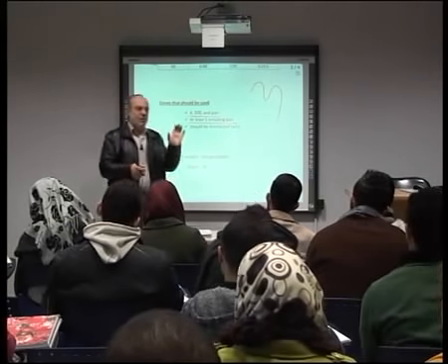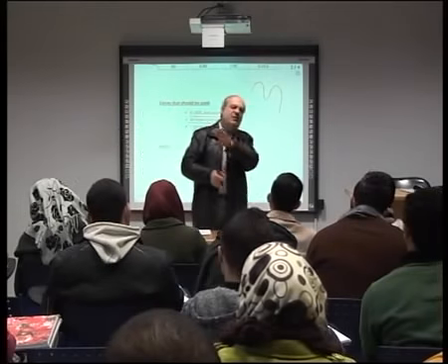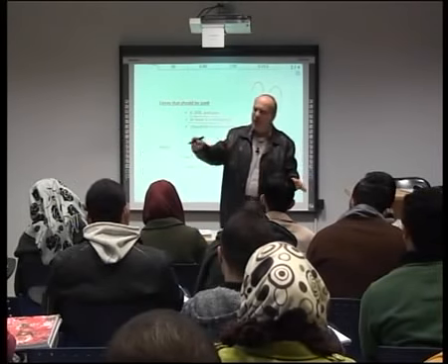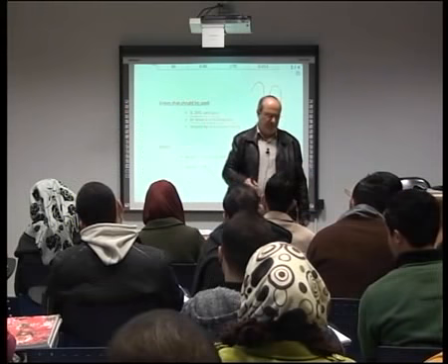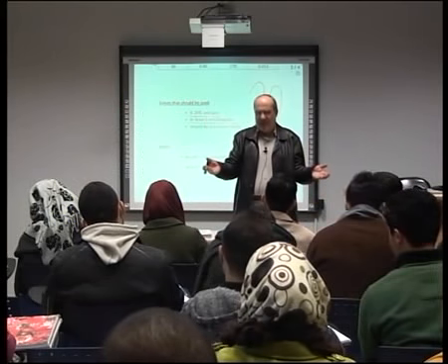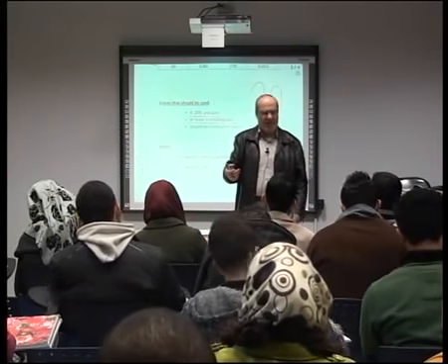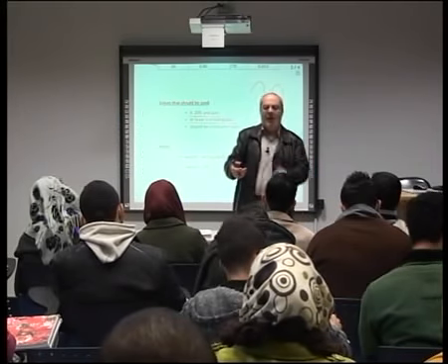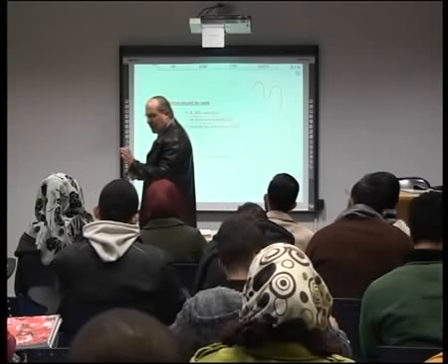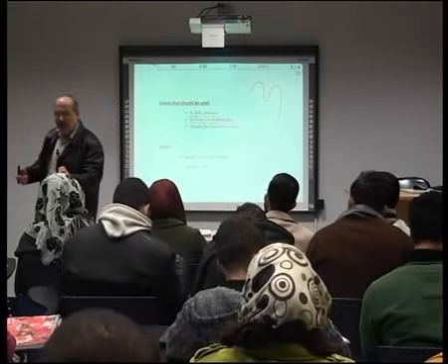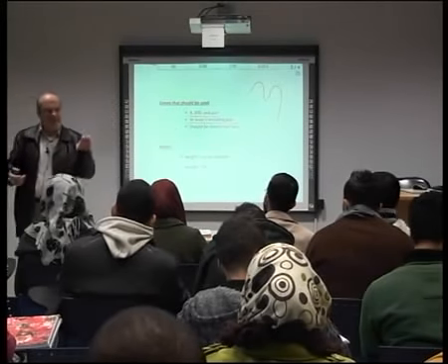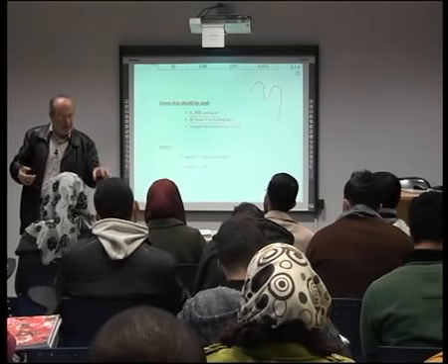Okay? I put 500 grams, they should not be 500.0000001. Because there must be a mistake. What should we do? Repeat the test. Okay? It is not allowed to exceed the total weight of the sample that was from the beginning put in the test.